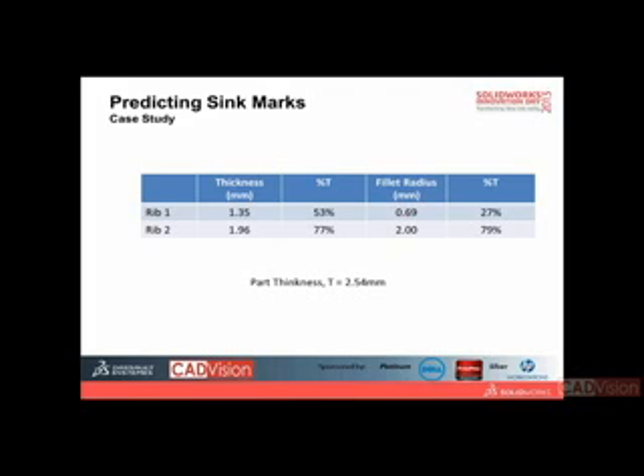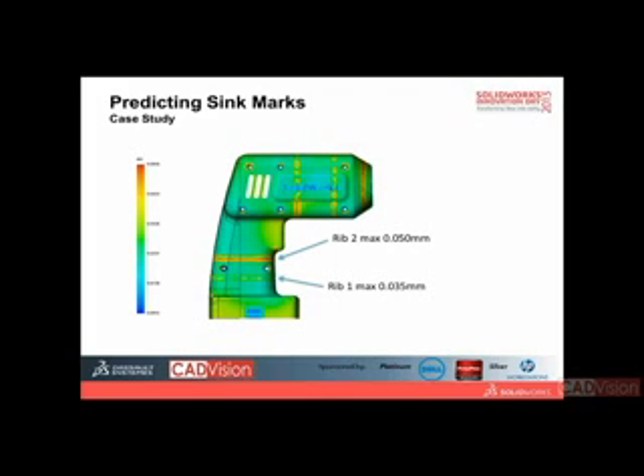For rib 2, it is just a little bit over, right? Both of them: two-thirds is 66%, it's 11% over, and 79% is 4% over. So it comes out as a result, there is a difference of more than 11%, right? 0.050mm and 0.035mm. The difference is more than the thickness difference. So we can see that their relationship is actually not linear. It's a 3D scenario because they are shrinking in all three directions, X, Y, Z. And it depends on the material. So we just decided a little bit over the design rule, but the outcome can be much more different.